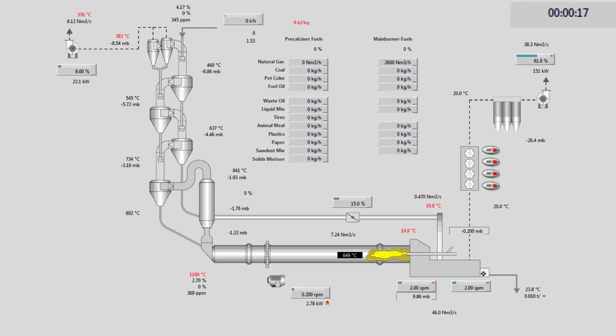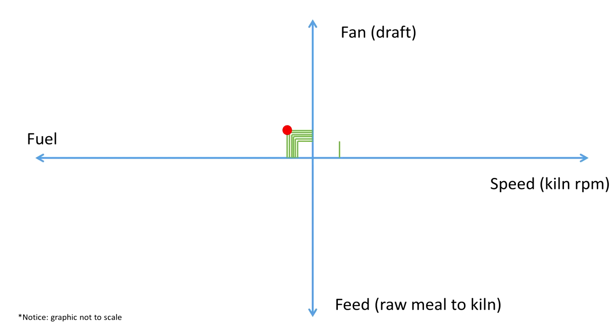How do I know that my system is ready to feed? I look at the preheater side and see it is very hot. Even with some tertiary air open to bring cold air from the cooler, I get almost 380 degrees Celsius on the ID fan. My system does not have a bleed air to keep my fan and filter cool, unfortunately. So I'm back to the theory, ready to feed. I will add more draft, fuel, feed, and increase the kiln speed.